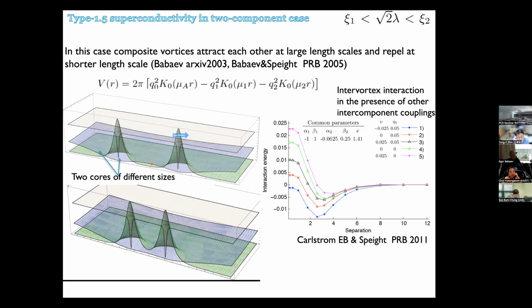You have a trampoline and you put 2 basketballs on the trampoline. They will depress the membrane and they will move close together. Or if you have 2 things on a sagging matrix, they will move together by depressing the matrix. Similarly here, we can calculate that intervortex interactions will be a sum of some Bessel functions, and so the vortices will attract. And this is interaction energy now coming from numerical solutions. At the large length scale, they attract.